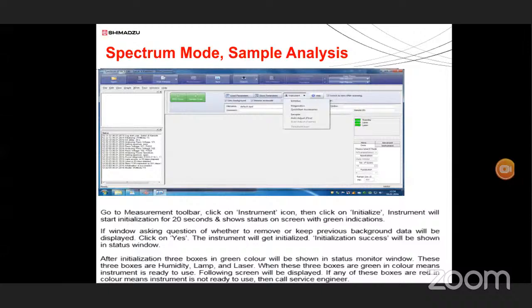Then after alignment, we have to run the software for the spectrum. Like in UV, before running the sample, we have to take the baseline correction. Here we have to take background or baseline correction, especially if we are using ATR. In general, we run the sample analysis on ATR. We put nothing in the sample compartment of the FTIR, no solvent or anything. You have to take the background of air if your sample is as such.